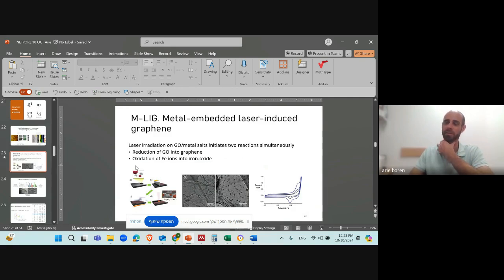So okay, then we wanted to make the material more interesting, not only carbon. So we added other things like metals. When you mix the carbon precursors with metal salts and laser it, two things happen simultaneously. It's very interesting. The carbon is being reduced, but at the same time, the metals are being oxidized or form metal oxide nanoparticles. Okay, so if you mix it and laser it together, you see this is a graphene and it is doped with metal nanoparticles.